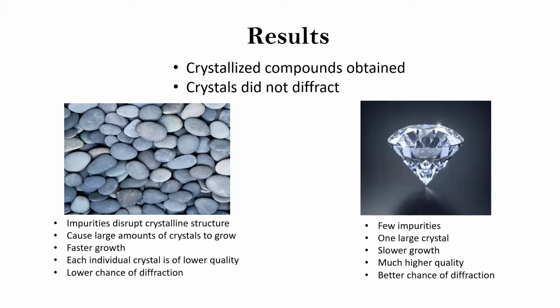As for my results, I have successfully gotten crystals, but when analyzed through X-ray diffraction, they did not diffract. This means that there was a problem with the crystalline structure itself, which is usually caused by impurities. Comparing the two figures on the left and the right, you can see the differences in characteristics between a good and bad crystal that impurities can cause.